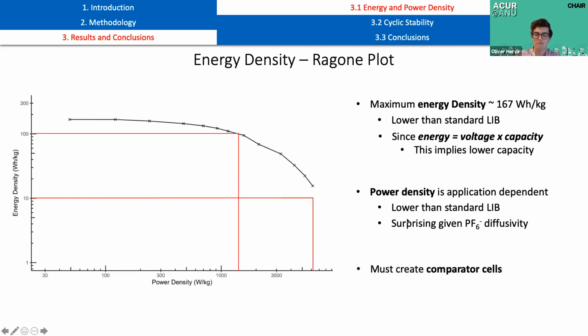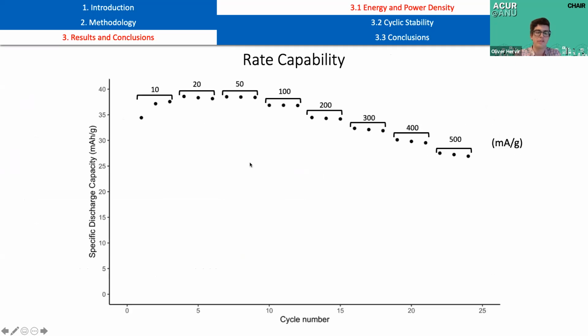Now, I keep referencing a standard lithium-ion battery, and that's because we were unable to create a comparator cell, or essentially a control, in our project. And this is kind of a next step that we need to do. This graph shows the rate capability, essentially the discharge capacity, or the number of charges, against a variety of different current rates. You can see that there's a clear peak here showing us that a current rate of 20 to 50 milliamps per gram is most optimal, and this peak also corresponds to the Ragone plot.